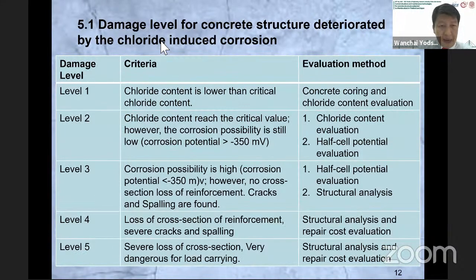In part 5.1, damage level for concrete structure deteriorated by chloride-induced corrosion, we have five damage levels, level 1 until level 5, and for each level we have criteria. And at each level of damage, we have an evaluation method.